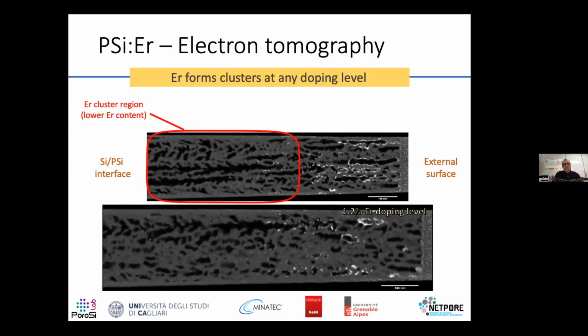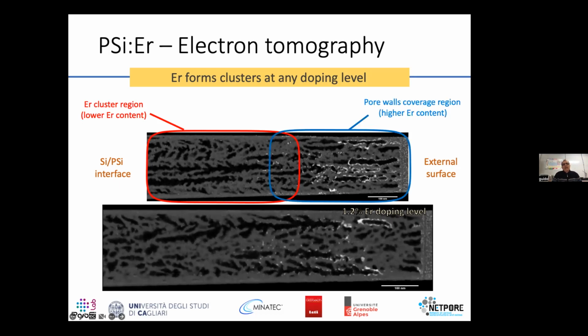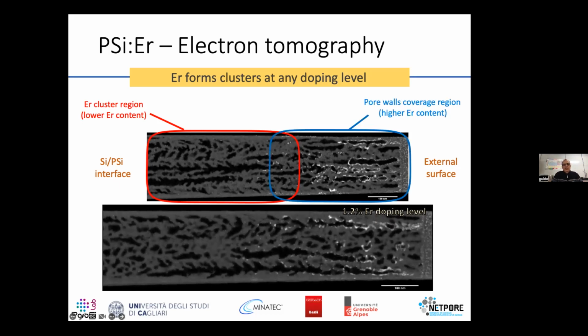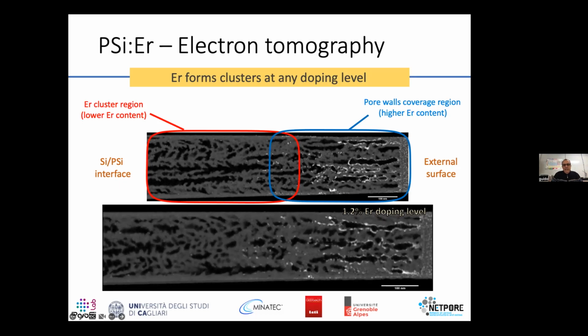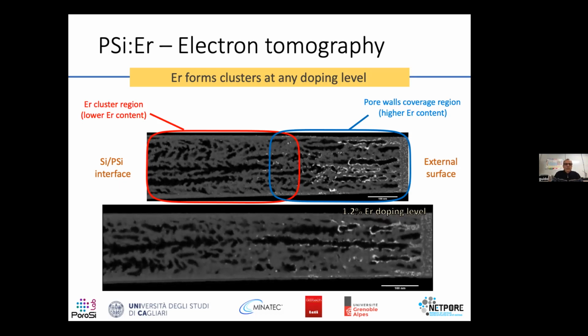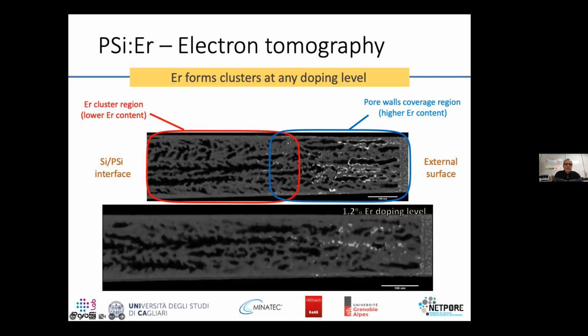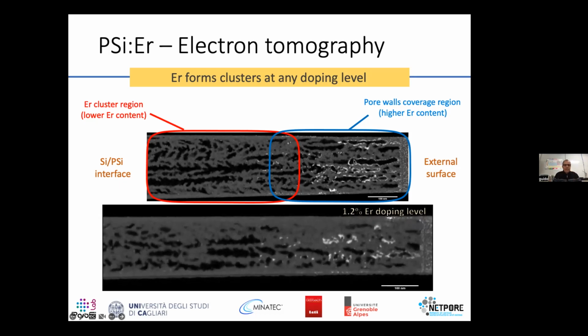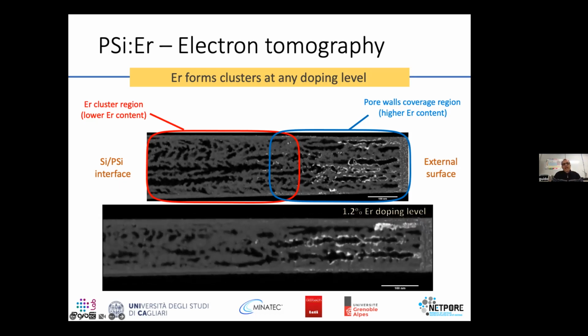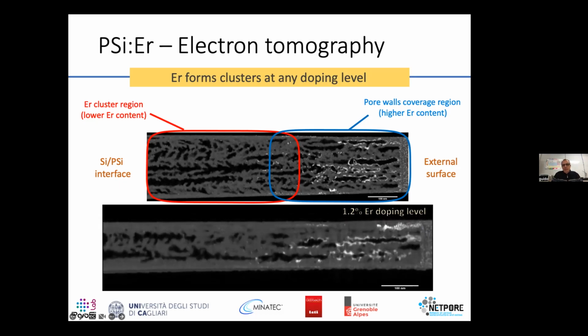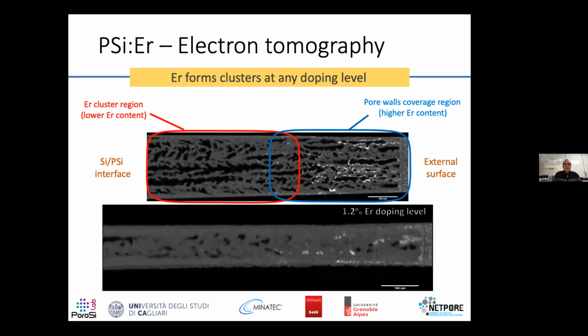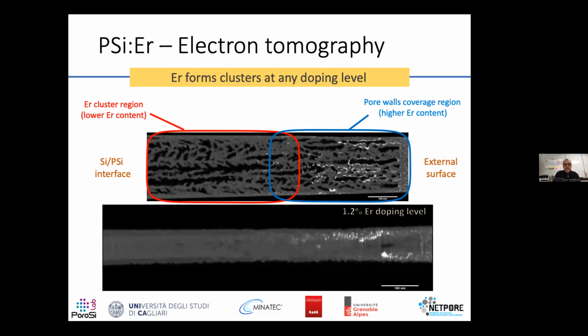So you can go to other regions where you have higher erbium content and try to understand how the doping behaves. And you notice that erbium nanoparticles coalesce and form a covering of the walls, while not clogging the pores, which is an important parameter why you want to understand how to fill at best your pores.